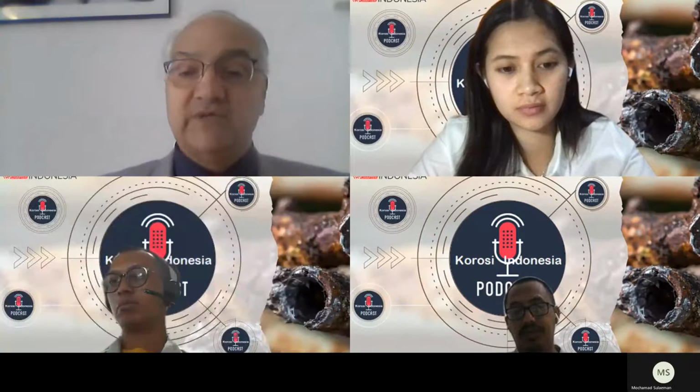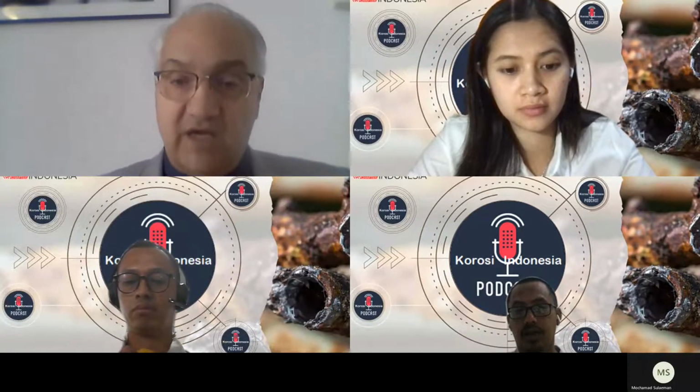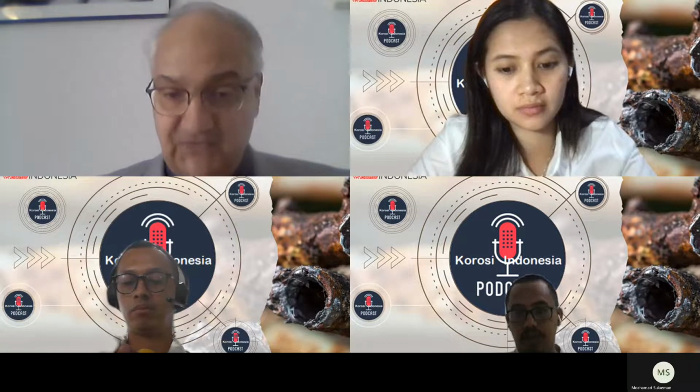Some people say that if, for example, in pipelines, you apply a potential of minus 950 millivolts versus copper sulfate, then it is highly likely that your pipe will be immune to SRB. No proof. No proof. We have cases where the applied voltage was even more negative than 1000 millivolts. Still, not only did SRB not die, they even became more active.